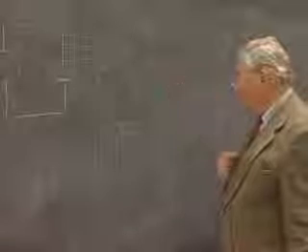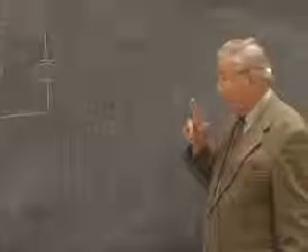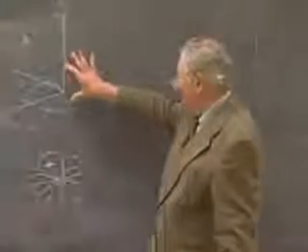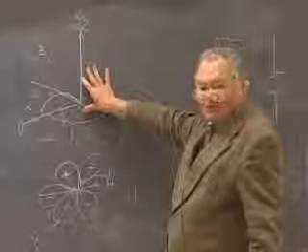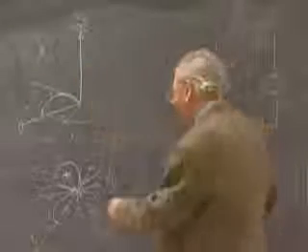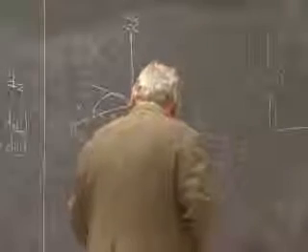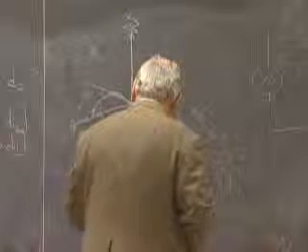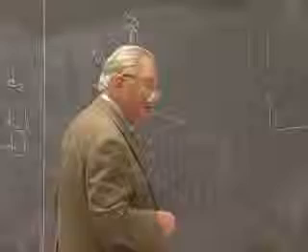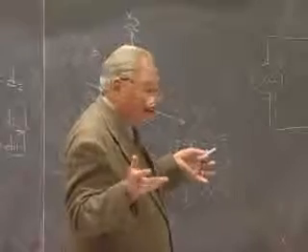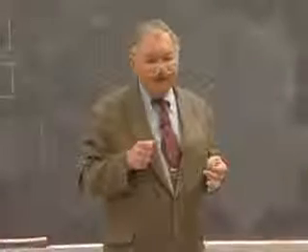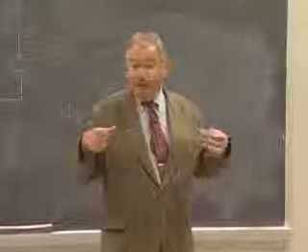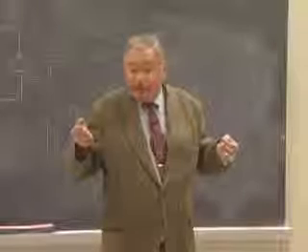This is a poor man's way of detecting piezoelectricity, but what if you happen to have your piece of quartz with the electrodes directly along the c-axis? The modulus would be 0, and you wouldn't detect anything. Or if you put on the probes such that they were in a direction that was in between these lobes, where again the piezoelectric modulus has gone to 0, you wouldn't find anything. So measuring the piezoelectric modulus for a random chunk of material is dangerous if you just look at one direction and say, oh, nothing's going on, it's not piezoelectric. The other thing is the material could have a piezoelectric response that's so weak you just can't measure it.